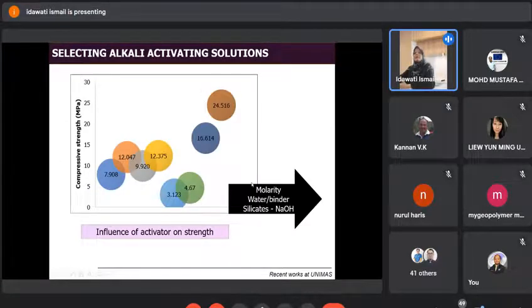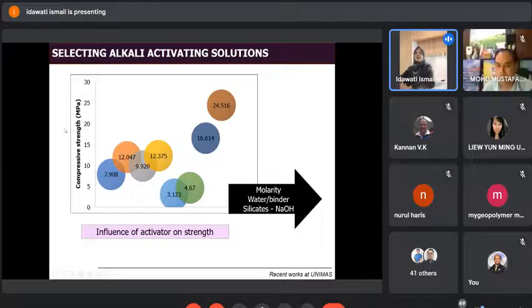Now, this is also one of our works at UNIMAS. This is a lot of mixes: molarity, water binder, some use silicates, hydroxide, and mixed. Our fly ash at UNIMAS is not very viscous. Under XRD we don't see much, it's not too glassy, so we have a problem with activating it. But when we put some silicate in our sodium hydroxide, we get a comparable compressive strength. Of course, this is on concrete samples, and we're still studying how we can improve the strength. The lowest strength here, around 3 megapascal, is probably very high water binder. So these are all the accumulation of a lot of results.